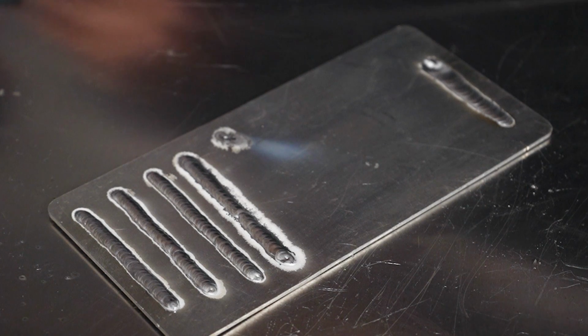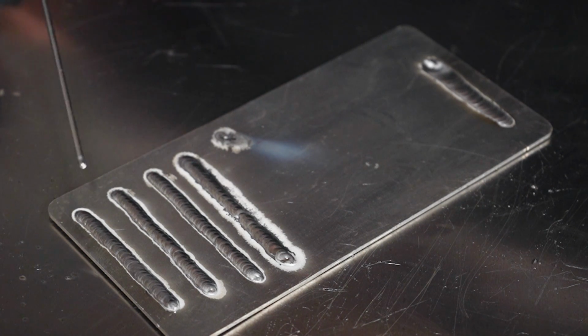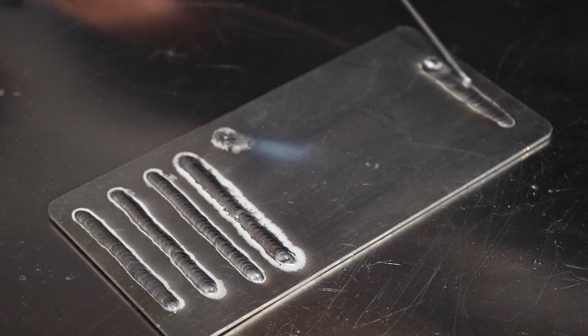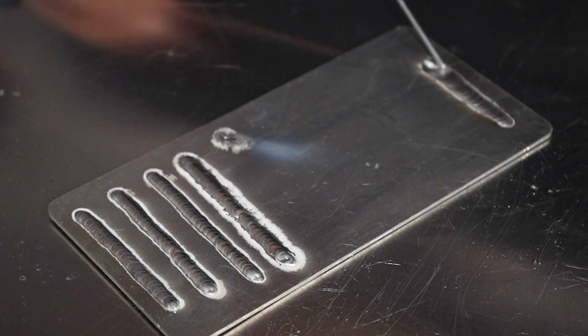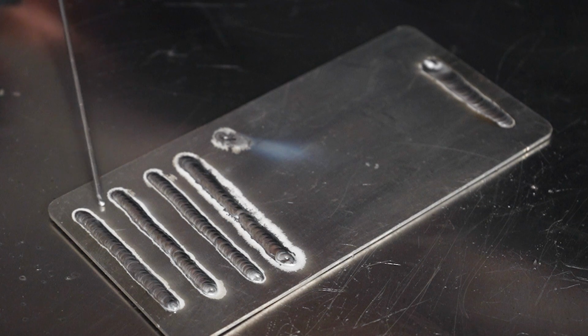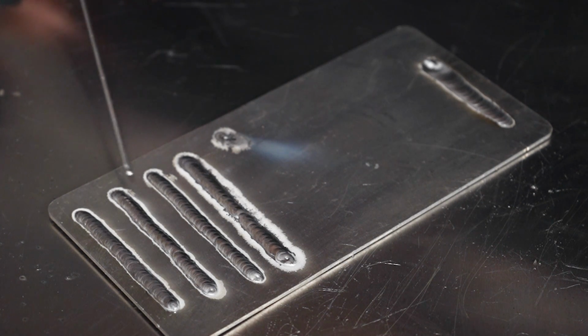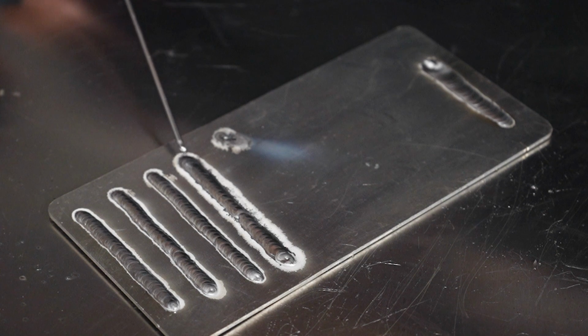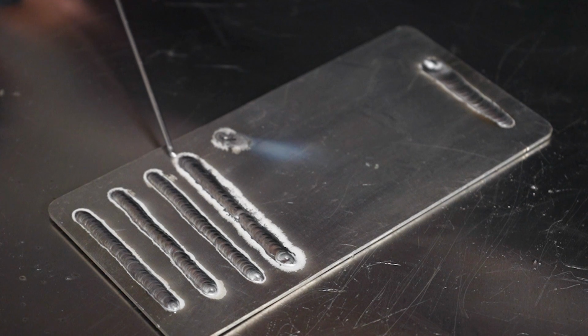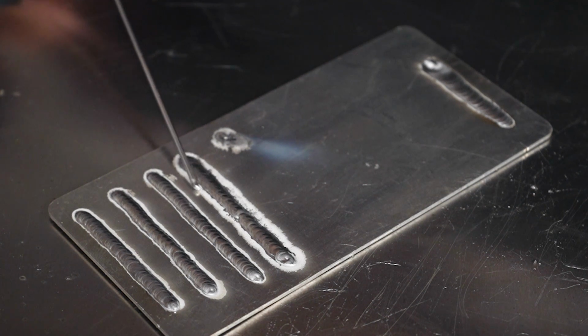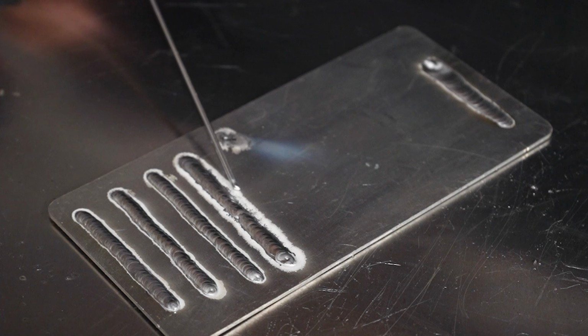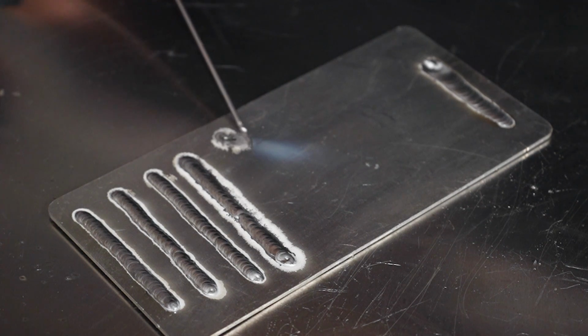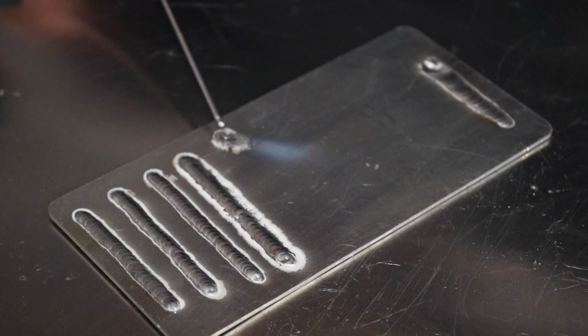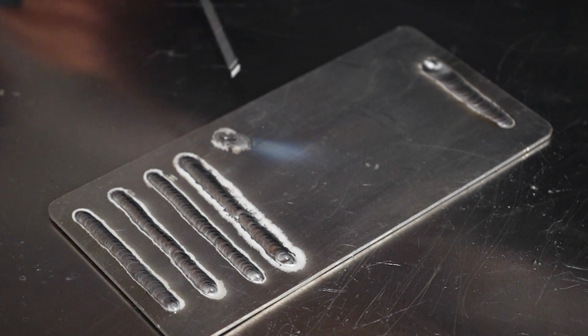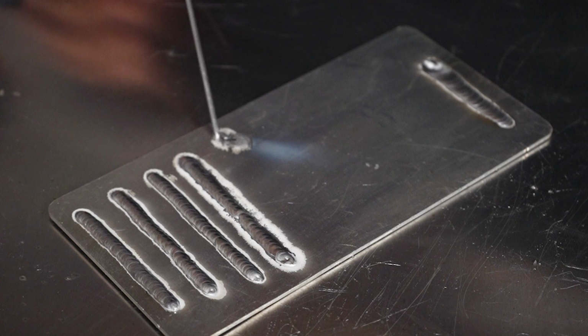All right, on this 6061 aluminum, we started way up here. That's at 60 Hertz, real wide bead. We went to 120, we went to 250, we went to 500 Hertz, and then we turned up our balance, which is our cleaning action. As you can see, when you turn up your cleaning action, 50% cleaning action really increased that etchant area. At 80% cleaning action, we just put too much heat right into the tungsten, caused that tungsten to ball up. That was too much electrode positive for this material and that diameter of tungsten.